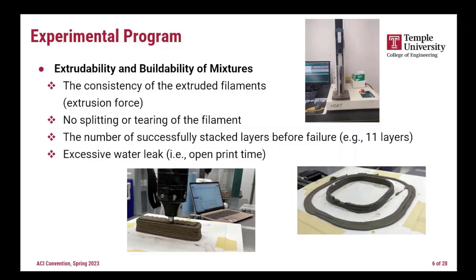So as we know, there are some challenges for developing the mix design for 3D printing compared to traditional concrete, obviously considering our limited experience with this. So for extrudability and printability of these systems, we consider these parameters, basically the extrusion consistency. We use the extrusion pressure. As you can see at the top right side, we use a similar system as Narayan discussed. Basically this syringe system, by displacing the ram, we can look at how the pressure changes over the print time.